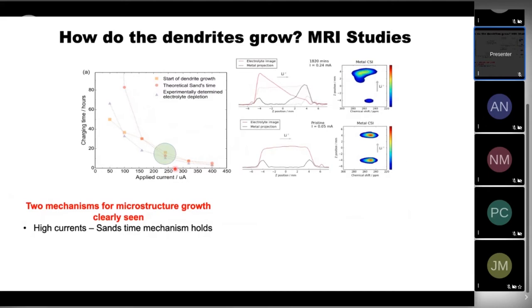And there's some theory associated with this where you can actually calculate the time in which you will go from mossy structure to dendritic structure. And the time this happens is called the Sand's time. And we can measure the experimentally determined Sand's time, or electrolyte depletion time. And you can see at low currents, our NMR experiments or MRI experiments fit those of the theory. So you might well then say, why don't you just decrease the current? And then you'd never get into a regime where you would actually see electrolyte depletion as shown here.